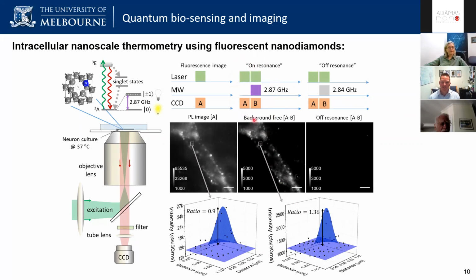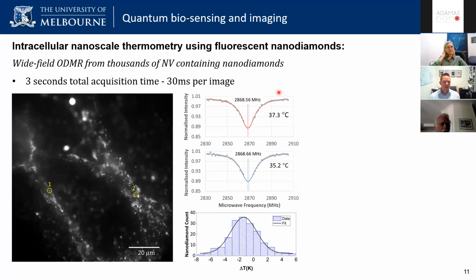And this is the exact sequence that we want to employ to do the thermometry. So if we're doing intracellular thermometry, we can do background free fluorescence imaging as well as then scanning this microwave frequency to infer the ODMR. And so we were able to show that, so here is a beautiful image of a neuron. So here's the cell body and the dendrite here, labeled with lots of nanodiamonds. And we were taking ODMR, wide field ODMR images from thousands of nanodiamonds at once. So whatever's in this field of view, we can infer an optically detected magnetic resonance spectrum from. So in this particular example, an acquisition time was about 3 seconds. So we were taking 30 milliseconds per point. And from that, we could build up these ODMR patterns, and we could monitor and follow individual nanodiamonds as the system was evolving.